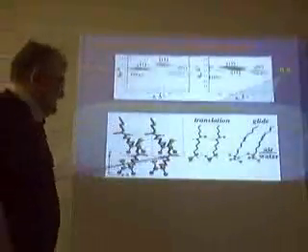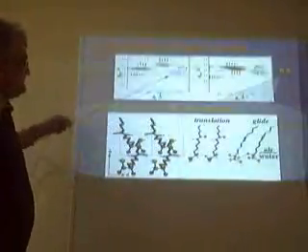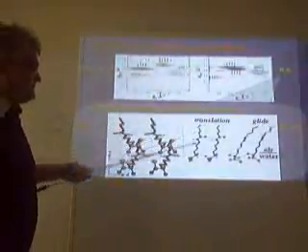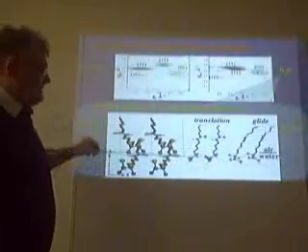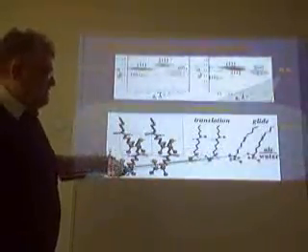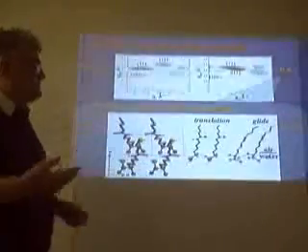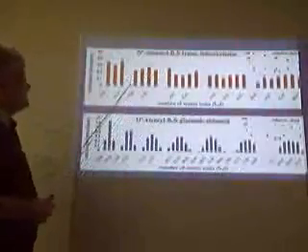And this was the structure that we could solve from these particular clusters. We found that the molecules are related in one way by translation, which will give the poly-L or poly-R or poly-S, and the other by glide, which will actually give you the syndiotactic one, which we got. And what we observed was that this was a distribution. Again, we got no more than 6 repeat units, but we could see, from the trimer, instead of having 1 to 3 to 3 to 1, we got 1 to 1 to 1. It was a nice